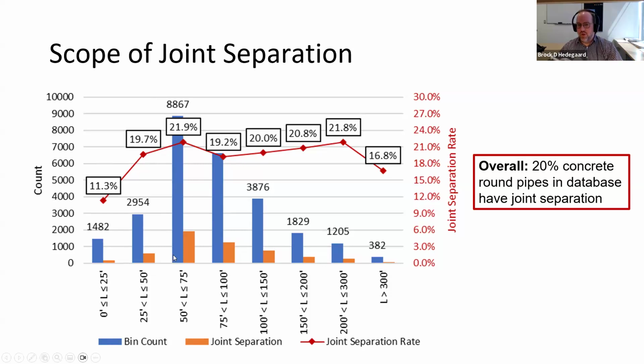And I should note these are all round pipes under highways. So that would be a typical, say, 2-lane highway pipe, would be generally in that range with lower fill depth. So if you have a very high fill depth, it starts to get longer. So most of your pipes are going to be between 50 and 100 feet in length. The orange bar here is the number of those pipes that have joint separation, and then the red line shows that percentage. So, for example, we see most separation in these 50 to 75 feet long pipes. So 21.9% of the pipes in that category would have joint separation.